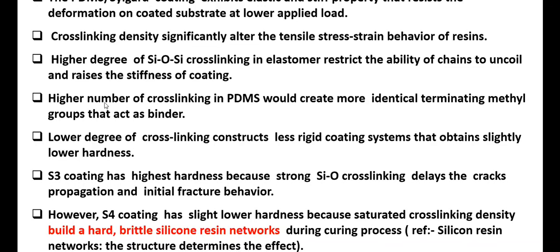Next, a higher number of cross-links in PDMS would create more identical terminating methyl groups that act as a binder. Because when the Sylgard which has been introduced in the PDMS becomes higher, it creates more identical terminating methyl groups that act as a binder. So a low degree of cross-linking constructs a less rigid coating system that obtains slightly lower hardness, and the S3 coating has higher hardness.